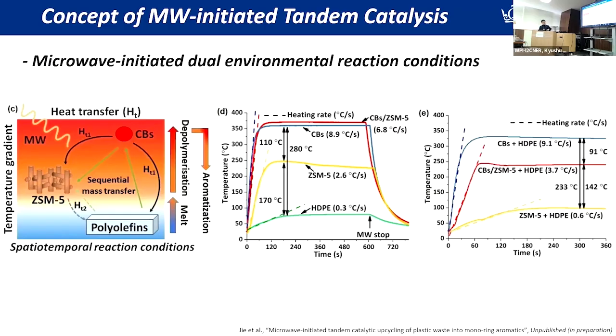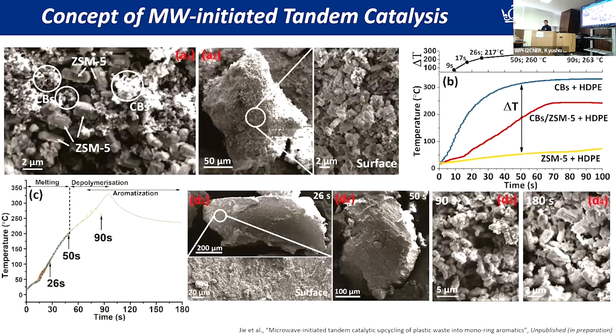So this demonstrates the heating profile of the different components under the microwave, and you can see the heating rate and the temperatures they can reach are very diverse. And this indicates that naturally this combination of the two materials could potentially create two reaction temperatures in a single vessel, and that will fuel the tandem catalyst and improve the reactions and the selectivities.